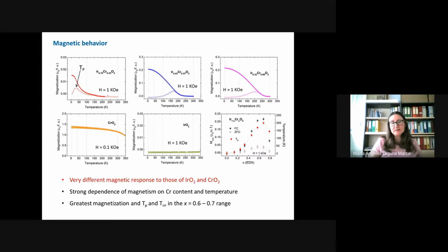And regarding the magnetic properties, as you can see in the top figures, in all the diluted films, there is a pronounced bifurcation between the field-cooled and zero-field-cooled curves. This behavior is very different from that observed in the parent compound, in the chromium dioxide, as you can see in the bottom left panel. The magnetization versus temperature curves present strong temperature dependence, which also depends on the chromium content. The maximum value reached by the magnetization increases with the chromium up to about 70% of chromium. After that amount of chromium, the system becomes mostly amorphous, and the magnetization decreases, as you can see in the bottom right panel.